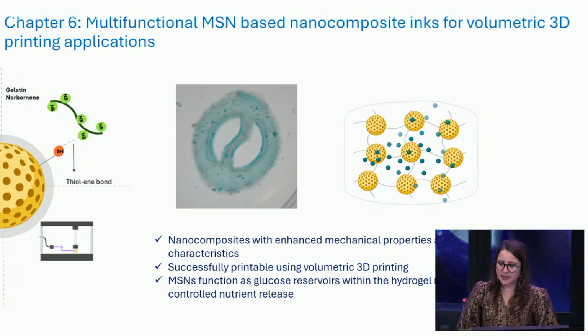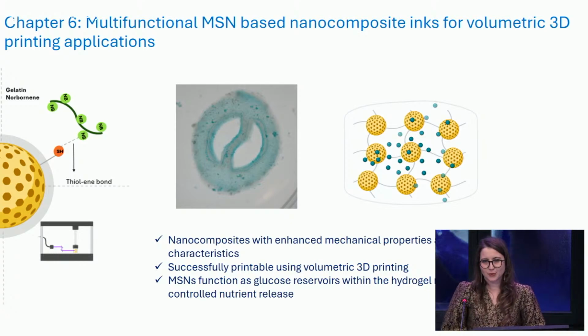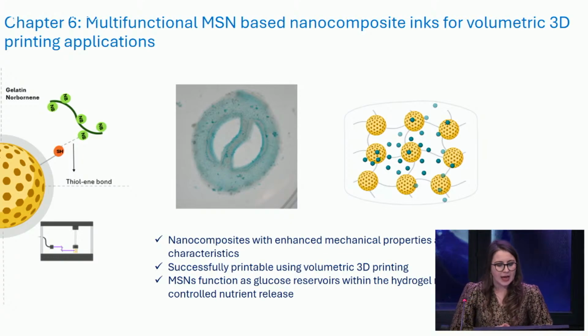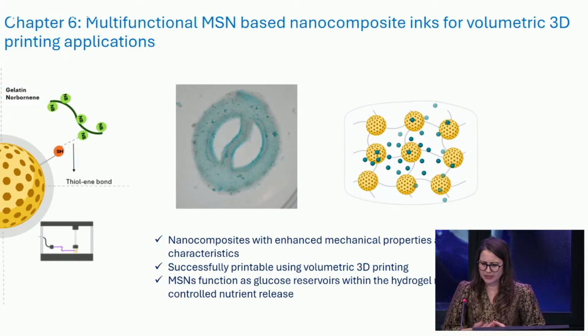By incorporating MSNs as covalent cross-linkers, we significantly increase the mechanical properties of these hydrogels. And importantly, for the first time, we successfully use nanocomposite inks to print structures by using volumetric 3D printers. And the next step was adding new functionality to this hydrogel system. So for that, I loaded glucose into the pores of MSNs and released it within this hydrogel network. So the idea was releasing glucose inside the hydrogel and enhancing viability of cells in environmentally challenging conditions, like during printing or post-printing.